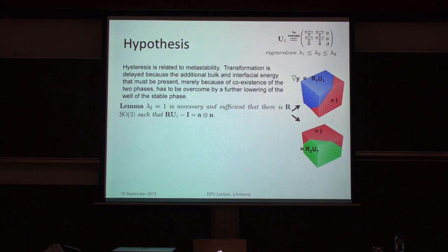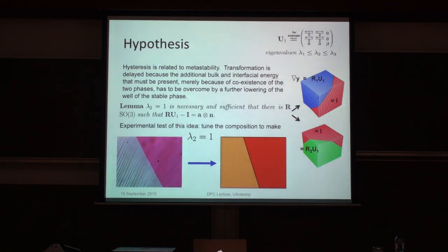Well, everything in sight, including this matrix and its middle eigenvalue, depends on the composition of the material. So you start with the material and you measure its lattice parameters with X-ray measurements and you compute lambda 2. And you see it's not 1. No material has it 1. And then you make another material and you do X-ray measurements and you measure its lattice parameters and you compute lambda 2 again. Maybe it's a bit closer to 1, maybe it's a bit further from 1. And as you can imagine, you can systematically change the composition to make it close to one. So basically, that's the picture which goes with that. And if that barrier is responsible for hysteresis, you should see a lowering of the hysteresis of phase transformations.